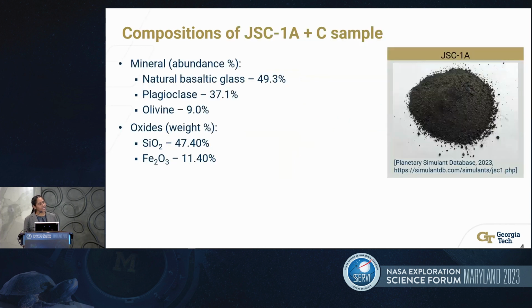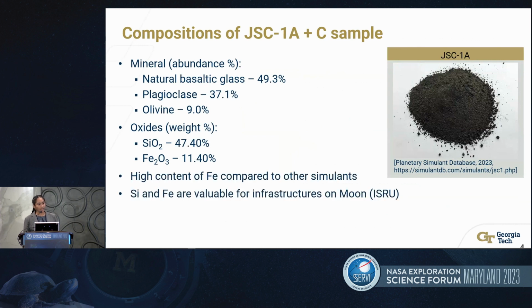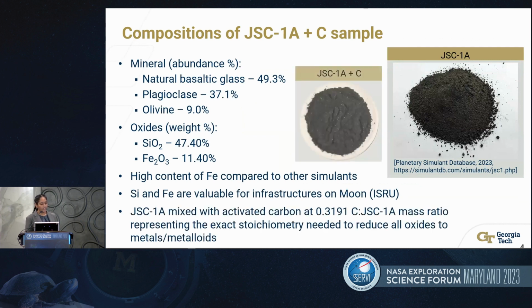Highlighting some key compositions, the JSC1A major minerals are glass, plagioclase, and olivine. In oxide form, the JSC1A has high amounts of silicon and iron oxide readily available for extraction. The high amount of iron differentiates JSC1A from other simulants. In our work, the simulant was mixed with activated carbon at about 0.3 mass ratio of carbon to simulant. This mass ratio represents the stoichiometric amount of carbon needed to completely reduce the simulant.